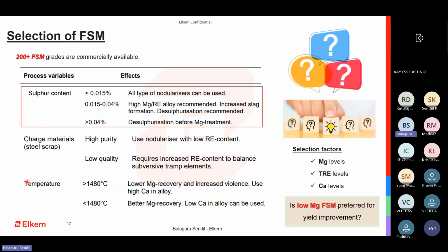So when it comes to yield improvement, a low Mg FSM is always preferred. So I put this as a question. I would explain why. When you keep the magnesium lower, we have discussed earlier that you have less shrinkage tendency and less carbides, less formation of slag and dross. So no need to go for additional filters, big risers, a direct impact on casting yield. When you are having low Mg, it is very easy to inoculate. You have high nodule count as well, which again is going to reduce your shrinkage.